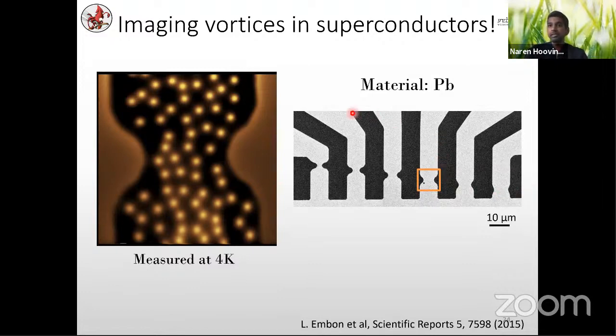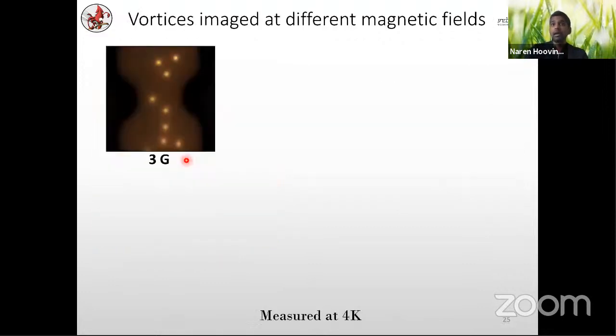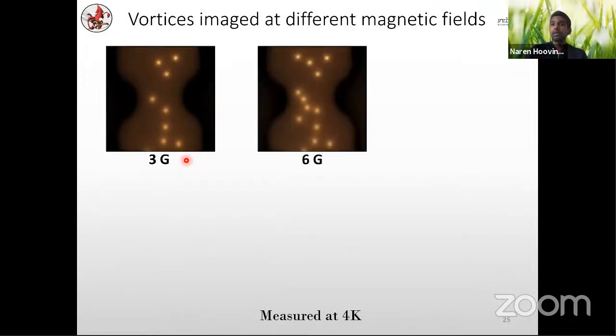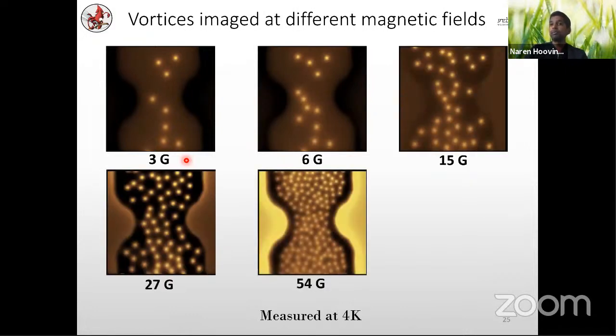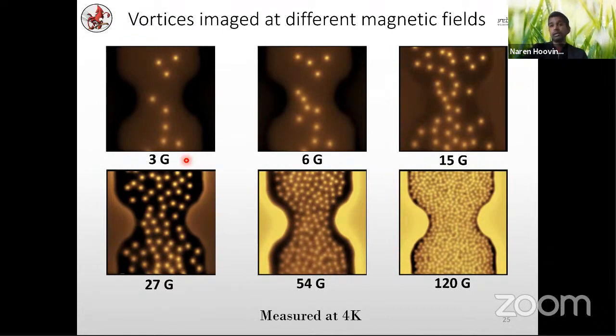So this is a lead thin film, which is patterned in this form with these hourglass shaped structures. The white part is actually lead and the black part is etched out. Now in this black part, when it's superconducting and you have a tiny magnetic field, you can see that the magnetic field actually enters the superconducting region in the form of these vortices. Then you can play around with that in several ways. For example, you apply less field, there are fewer vortices. You apply more and more field, and then you can have more and more vortices in that region. These are all very quick scans. Actually, these scans can be performed in around 2 minutes or so, and within 2 minutes we get such a beautiful plot.